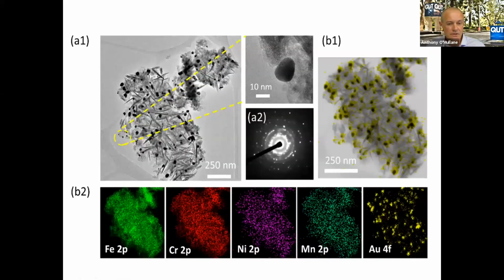And if we look at TEM of that sample, after we've done our gold modification process, again, we can see those nice flakes of the layered double hydroxide material, and then these little parts here are small gold nanoparticles distributed throughout that material. Our distribution of iron, chromium, nickel, and manganese is quite even across that sample, and then we have decoration of gold throughout our particular sample.